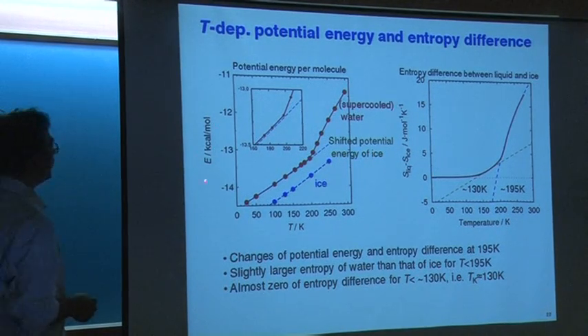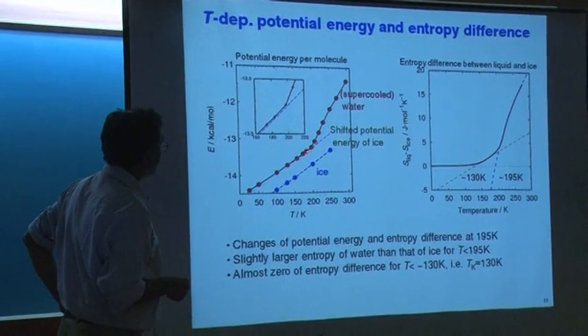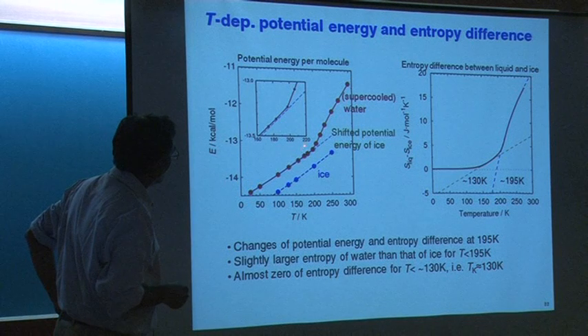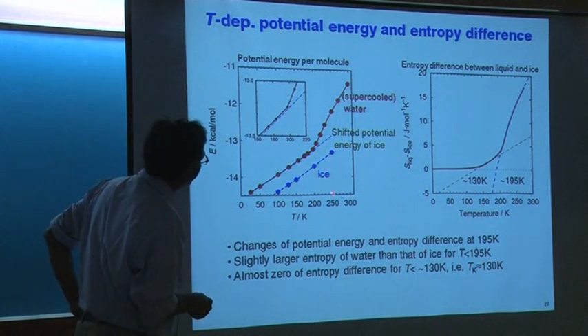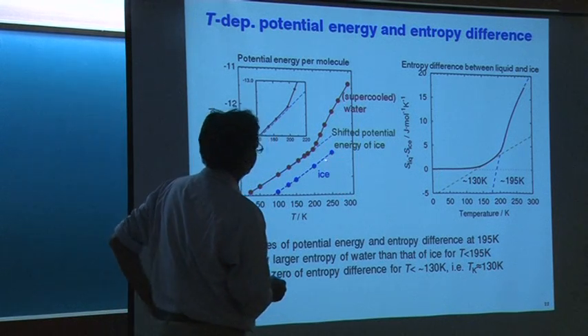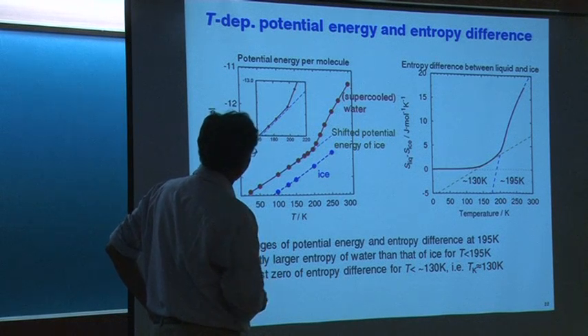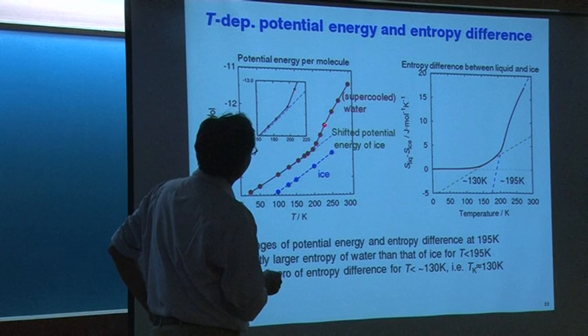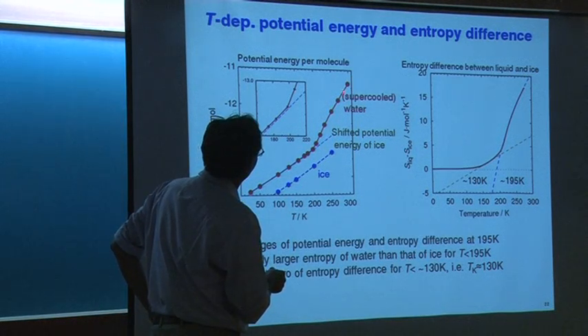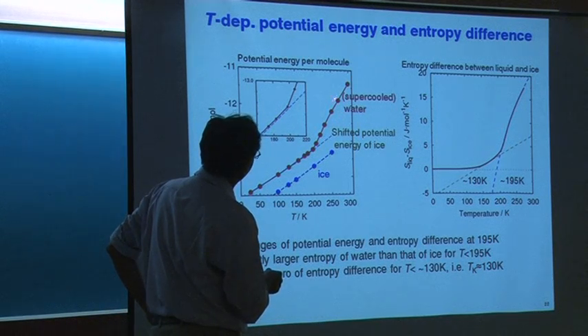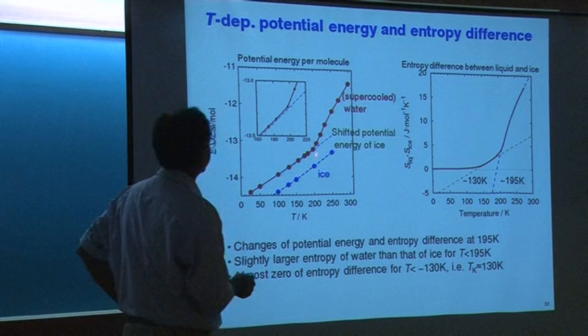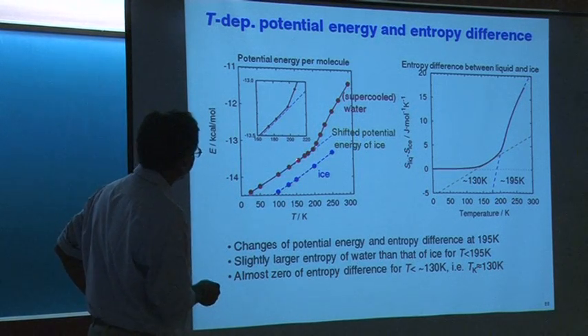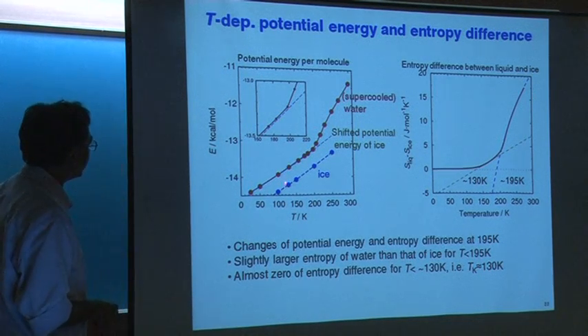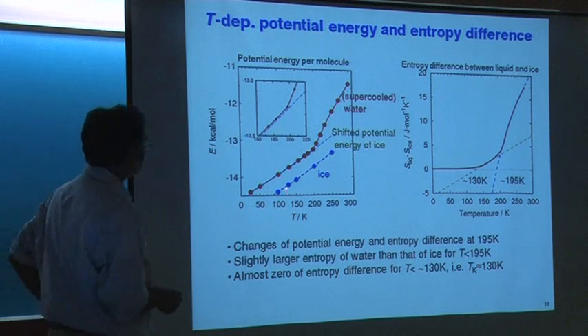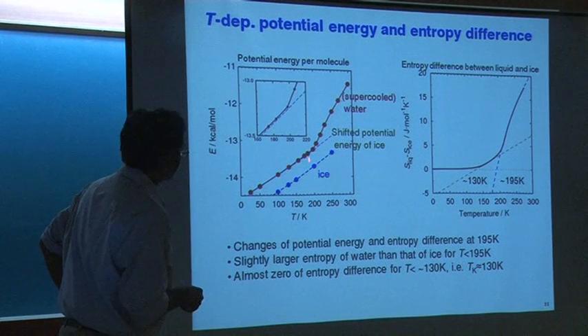Now these are plotted, the potential energy per particle or per mole of water and ice. This is ice. Look at that, when I go to lower temperature, it continues like that, and ultimately at 273 Kelvin, I go a little bit here, and this is why it melts. It melts into water. This is ice, the blue one. But this is my supercooled water. Ordinary water becomes supercooled. But look at the change of the potential energy. Then it's very interesting. At lower temperature, there is a 0.5 constant offset between the two. Here is glass. I'll come to this glass transition now.